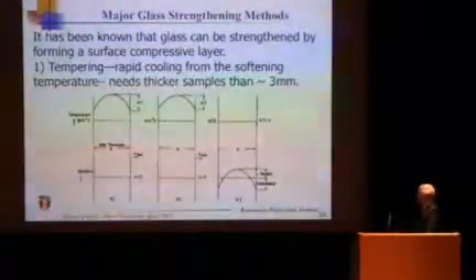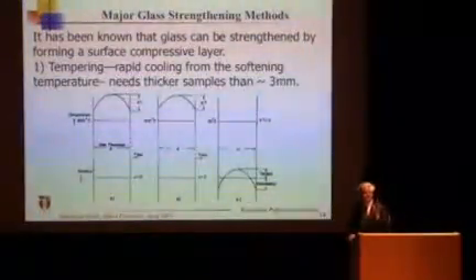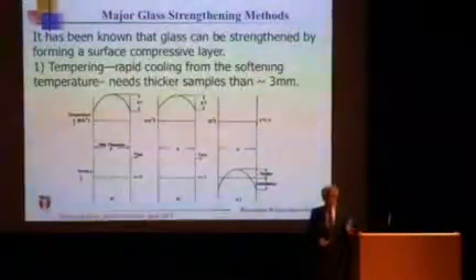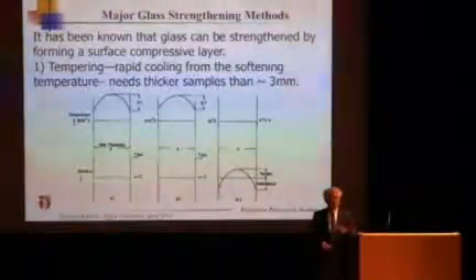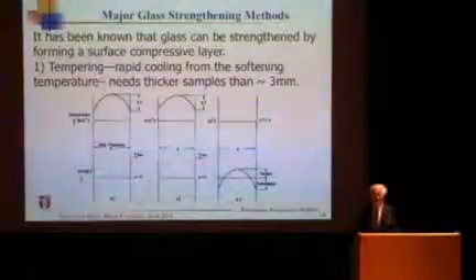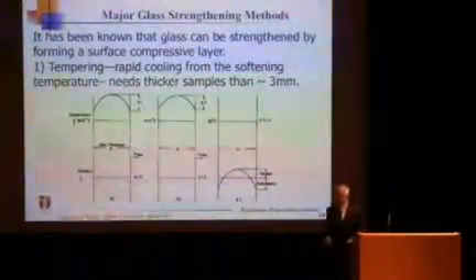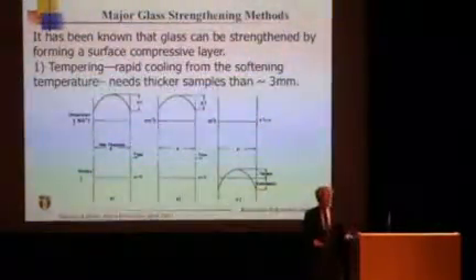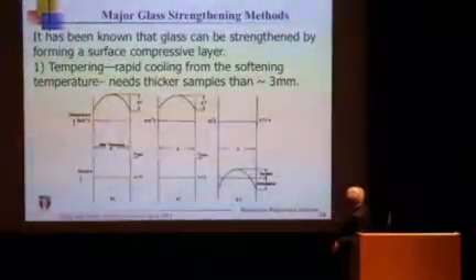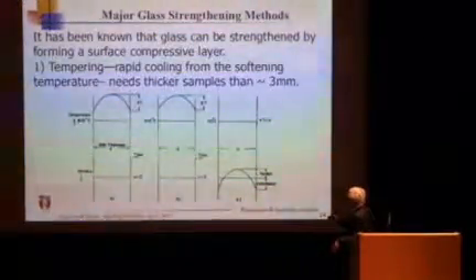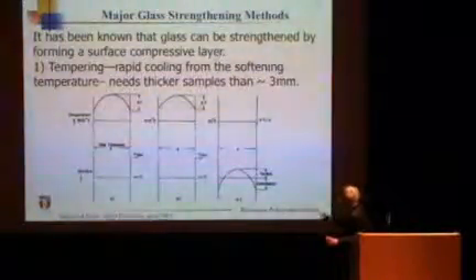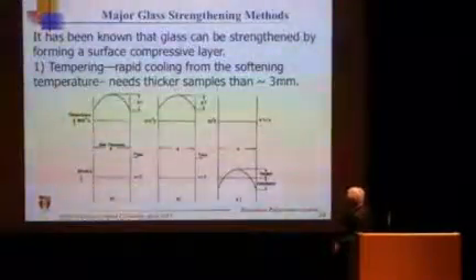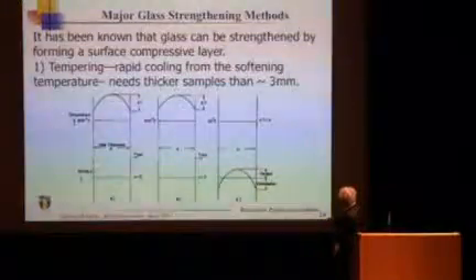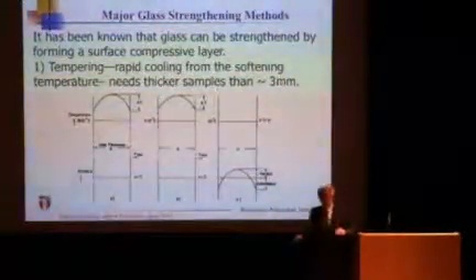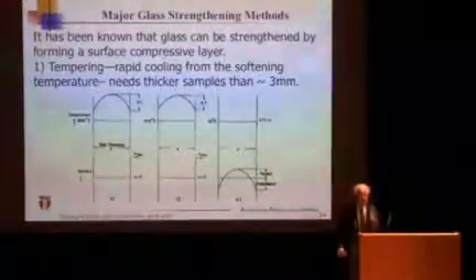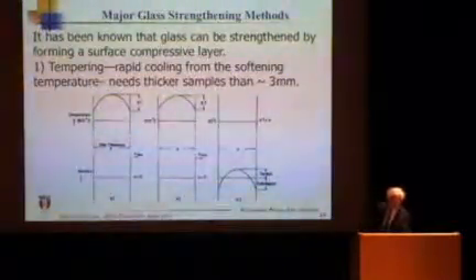As I was saying, there are 2 well-known ways to make glass stronger. One is tempering. You take a glass plate to softening temperature, rapidly cool, and then the glass becomes stronger. That type of strengthened glass is used in automobile side windows and rear windows. Of course, when you break it, it shatters into pieces because of the high stored energy. To make such high-strength glass by tempering, you have to have 3 millimeters or thicker, because what's happening is a temperature gradient when you're cooling. If you rapidly cool, the center portion stays at a slightly higher temperature than the outside, but this is high temperature, so stress is not maintained. There's no stress. When you keep cooling, this temperature profile continues until room temperature, and there's no stress. Then the center has to cool down to the same temperature as the outside. That produces tensile stress. So if you have a very thin specimen, you can't strengthen a glass plate by tempering.